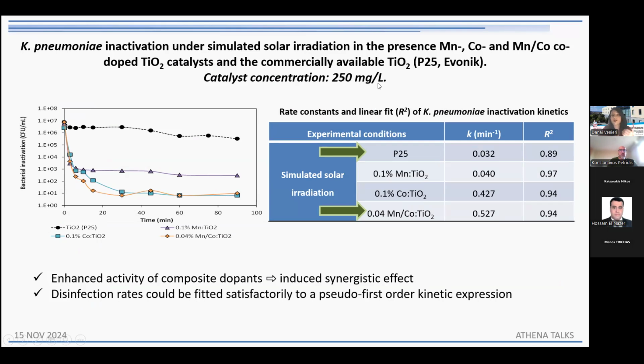But just to highlight, take a look at the really higher concentration of the catalyst. In the previous slides I showed you, we used 25 or 50 milligrams per liter. In this case, we used a higher concentration, which means what? That antibiotic-resistant bacteria might be quite resistant against the disinfection technique. And I underline might be, because we cannot say one rule. We cannot have one rule for every single bacterium because of the great variety. Nevertheless, in this case, we saw that solar photocatalysis was quite effective, at least with the use of certain catalysts.